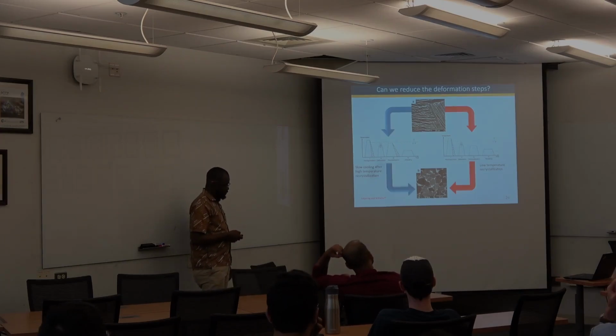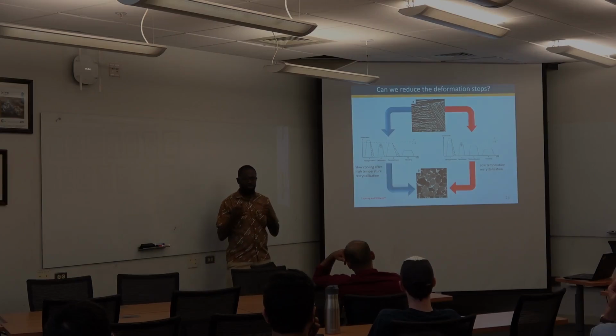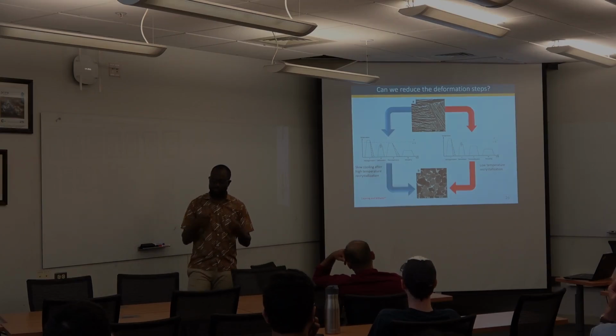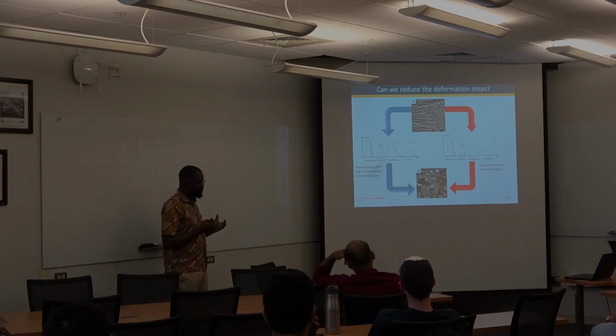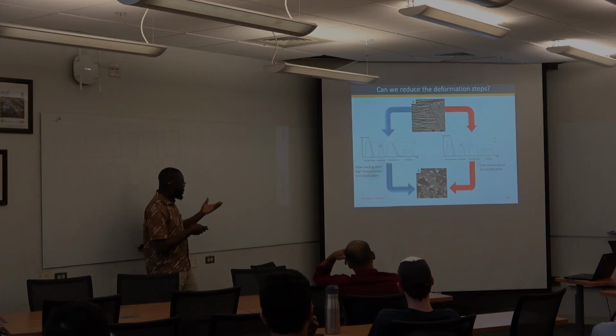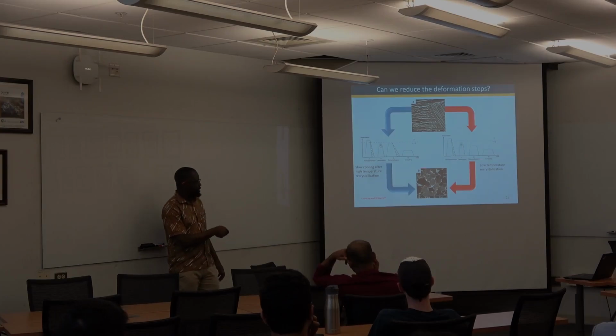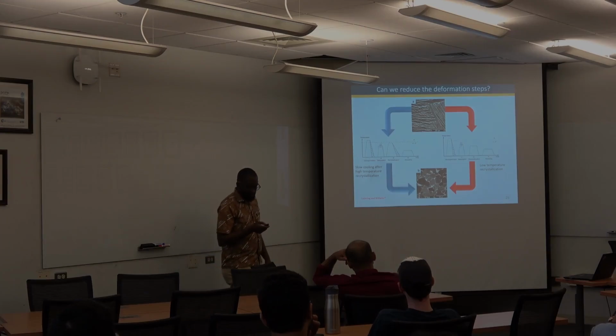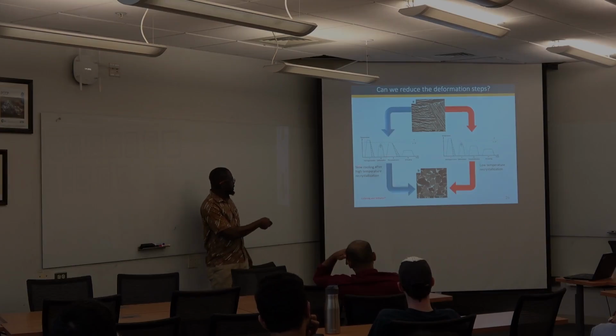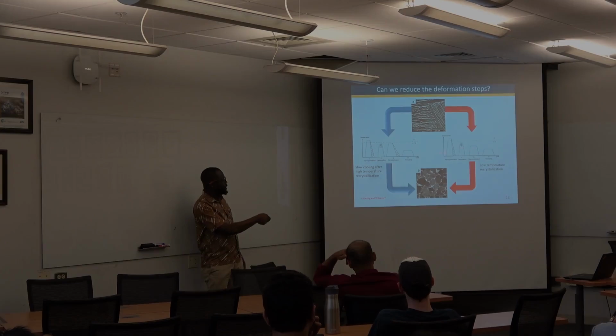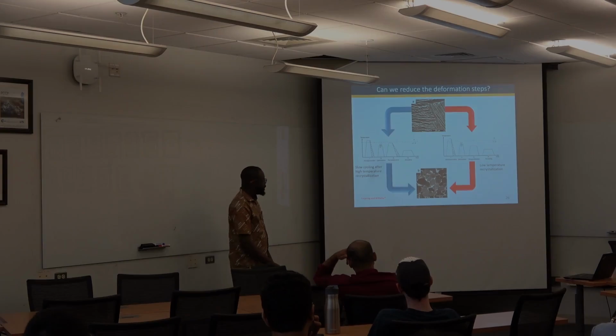So, if you read the titanium textbook quite well, if you have a lamellar structure and you really want to improve the ductility and the deformation properties in general, you desire this kind of microstructure, which is an equiaxed microstructure. And if you follow the standard textbook on titanium by Boyer and Williams, you see that you can arrive at this microstructure following either of these two routes. And this is usually what you have in the as-cast state, basically.